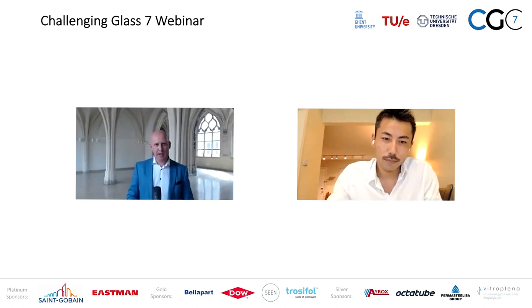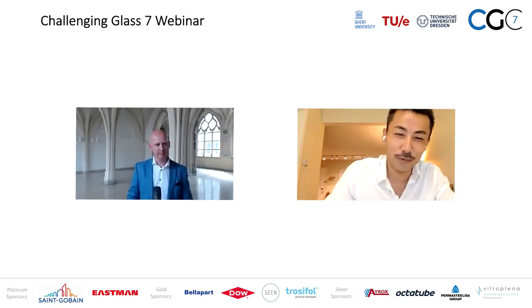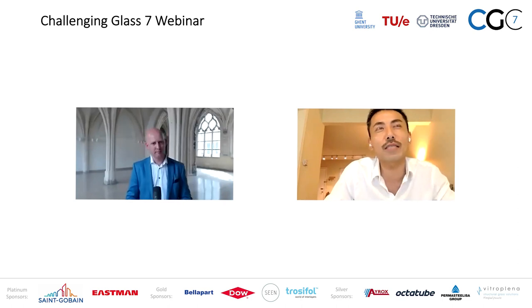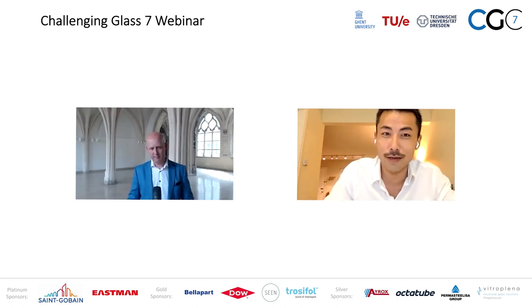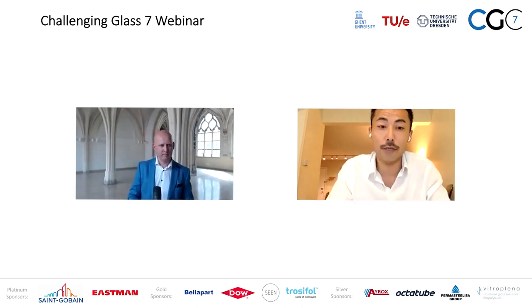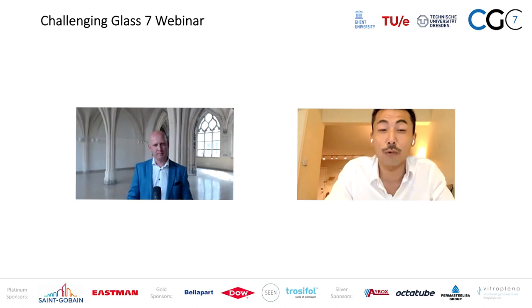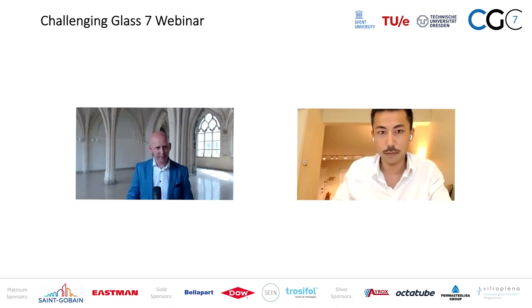Have you tried to print on soda lime silica glass sheets? So print on a glass sheet to, for instance, stiffen it? Yes, we have tested a couple of those. And we also began speaking with researchers who are developing what they call glass welding of soda lime window sheets. It is technically feasible so long as we elevate the temperature of soda lime glass windows or window panels up to close to working point temperature before we deposit the molten glass. Otherwise, it'll cause a thermal shock.